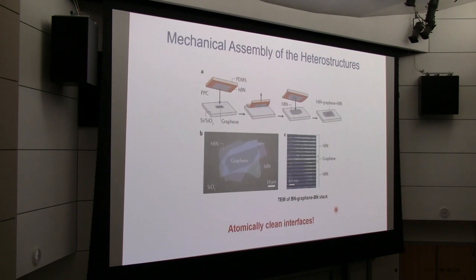And indeed, researchers found it's possible, using rather simple materials like a plastic, that you can pick up individual thin layers of this 2D material, one on top of each other. And then you can release them onto the substrate and form, indeed, this Van der Waals heterostructure. And when you take a closer look at this heterostructure, it's almost as good as shown in the cartoon. They actually have atomically clean interfaces, as shown in this TEM image. To some extent, that's one of the biggest surprises of these 2D materials.